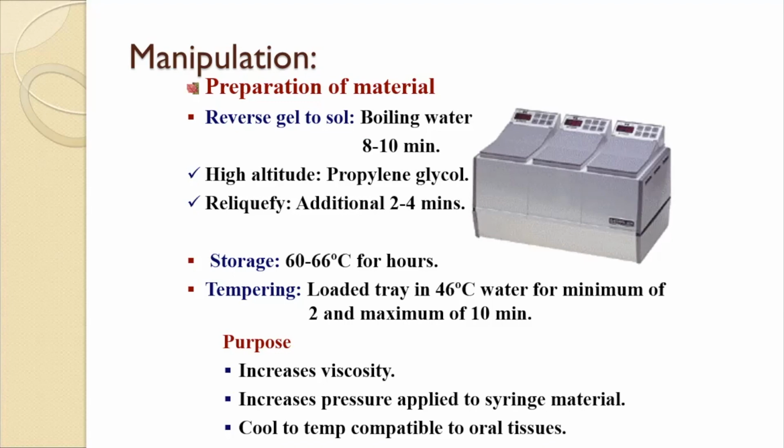Normally, the temperature of the syringe material is cooled sufficiently as it is extruded so that it is comfortable for your patient. The syringe material is first applied to the base of the preparation and then the remainder of the prepared tooth is covered. The tip of the syringe is held close to the tooth and it remains embedded below the surface of the syringe material to prevent entrapment of bubbles. You have to keep that in mind as well.